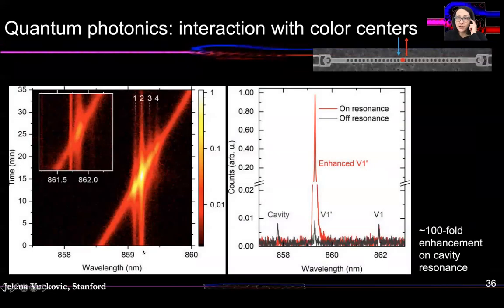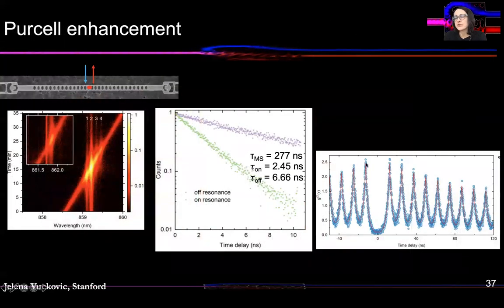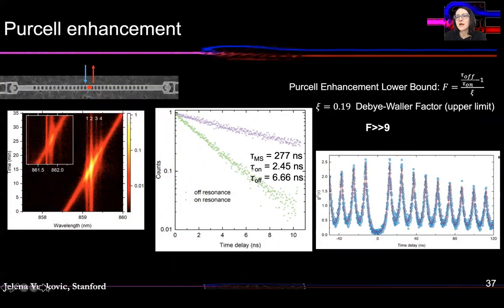As for quantum photonics, we have shown that we can couple color centers to these silicon carbide circuits without degradation. When they are in resonance with the structure, their emission is enhanced by a factor greater than 100. Their lifetime is reduced. We see strong Purcell enhancement.